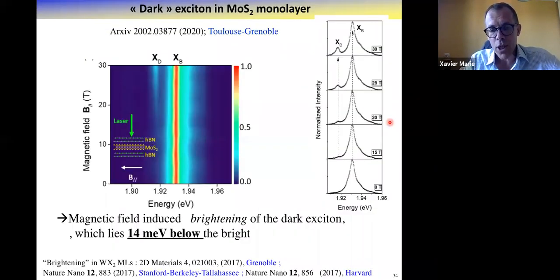And just before switching to bilayers, very recent results, because for many years we tried and many groups tried, you have many, many calculations in the literature about where the dark exciton is in MoS2. Because so far we had a clear fingerprint of the dark exciton in WS2, WSe2, but for molybdenum-based monolayers, it was an open question, with many controversies about this. So recently we worked with our colleagues in the high magnetic field lab in Grenoble, fabricating very high quality samples, again encapsulated in hBN, and we used the very classical technique, which has been used for more than 40 years in semiconductors. How can you evidence a dark state if it's dark? Just by applying a magnetic field to mix this state with a bright state.